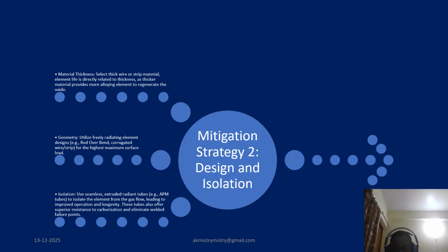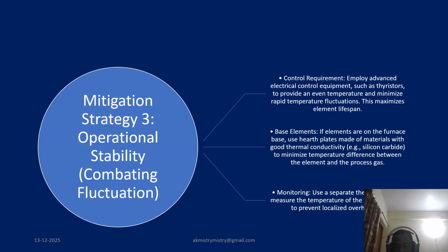Now coming to the mitigation strategy number 3. So to actively combat the temperature fluctuation, we must employ an advanced electrical control system, especially thyristors, which can provide an even temperature and minimize rapid changes. This stability directly maximizes element lifespan. Additionally, if elements are placed on a furnace base, we must use a hearth plate made of material with a good thermal conductivity like silicon carbide to minimize the temperature difference, and use separate thermocouples to prevent localized overheating.